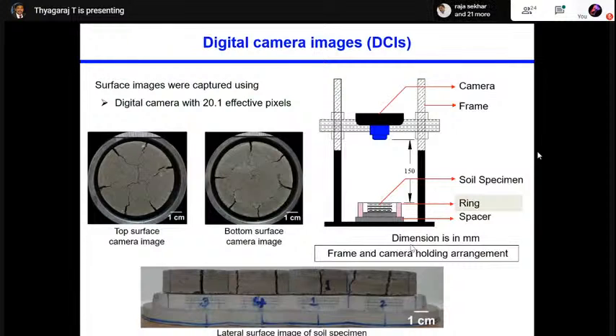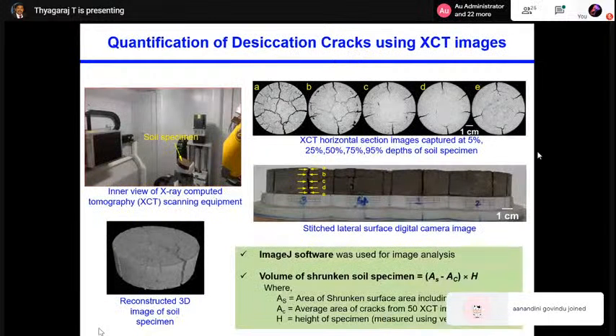You can see that we have used a simple digital camera, which has 20.1 effective pixels. This is the arrangement. The camera was kept about 150 mm above. The sample was here in the oedometer ring. You can see that images were captured at different timings. The left side one is the top surface camera image, and the right side one is the bottom surface camera image. And we have also taken out the ring. We have taken the lateral shrinkage also, and we have stitched them together to get the lateral surface image of the soil.